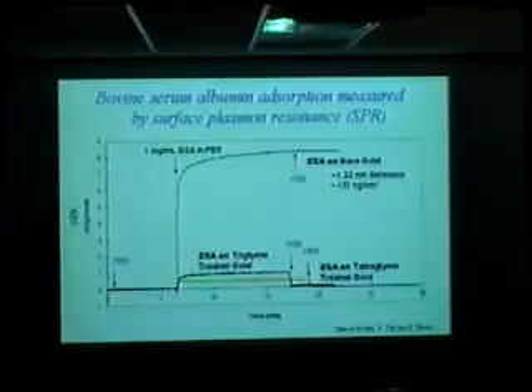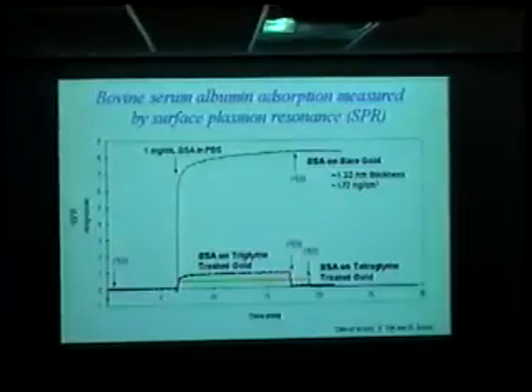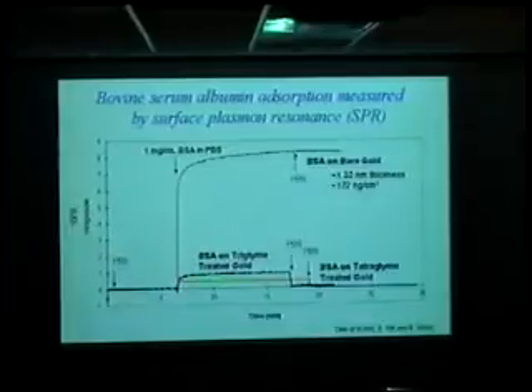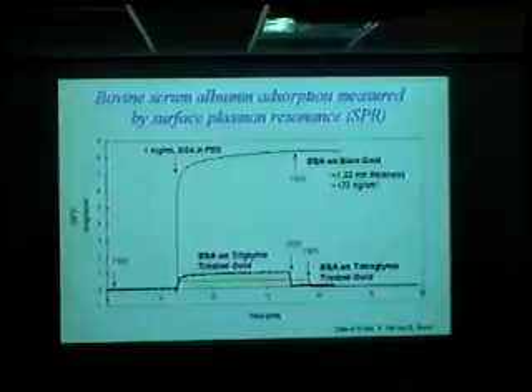We take this gold, put it into our plasma reactor, put on a coating of glyme. Now we have our buffer. We add the BSA, small signal. We add buffer, it goes right back down to baseline. This is called triglyme, three of those ethylene glycol units. Tetraglyme, that's the yellow bar, even less pickup when we add the protein. As soon as we add the buffer, right back down to baseline. These are pretty non-fouling materials.